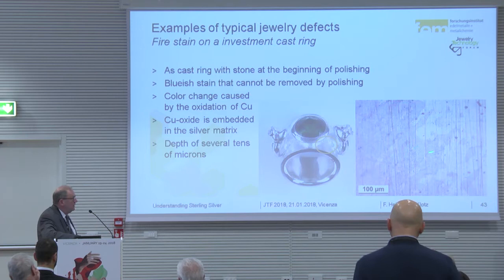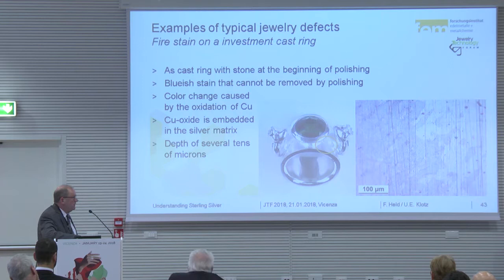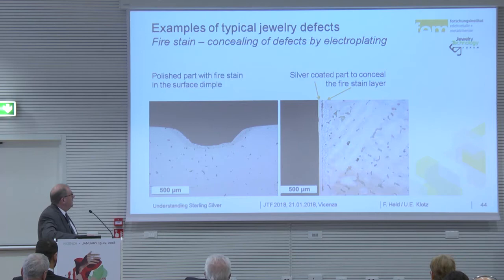After polishing, you see here normal material as we want to have it. Here, fire stain, which means it's silver with copper oxide. This was this area. Normally, if we want to remove fire stain, it's possible. But if you have here a line for designing, you can polish on the top surface, but not inside of the line. This will be shiny blue, and the rest, which is silver.